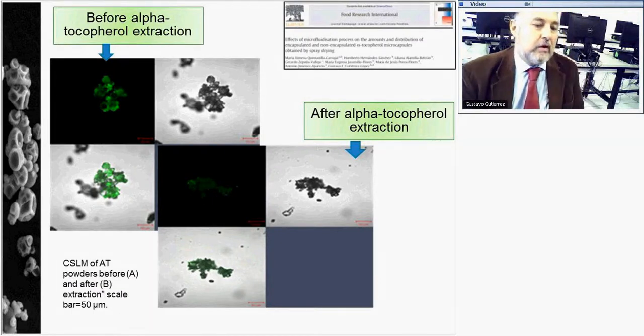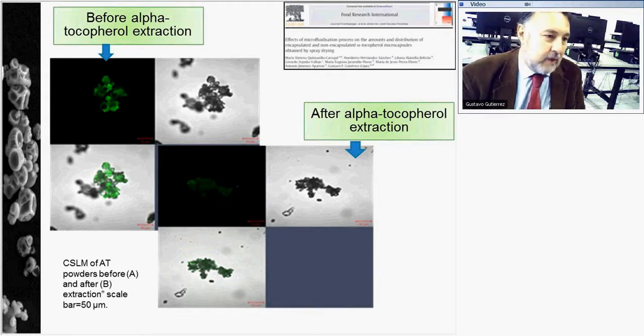The work of Jimena Quintanilla: she did an extraction of alpha tocopherol from capsules that she spray dried, which contained alpha tocopherol on the interior of the material. So, confocal laser scanning microscope images of the particles before and after the tocopherol extraction. This was very interesting because we see that a good part of alpha tocopherol was found at the surface of the particles.